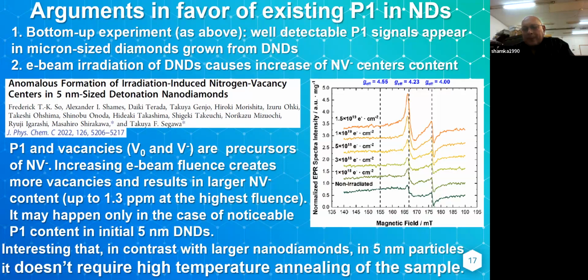Why? Because there are not enough centers in comparison with P1 to apply the indirect exchange to NV minus centers. I think that maybe at very high densities, if at high fluences you can achieve higher densities of NV minus centers, you may see something. But when you have 1.3 ppm, it's nothing in comparison with the initial 130 or 900 ppm in DND. There are interactions, but they cannot change the spectrum itself.